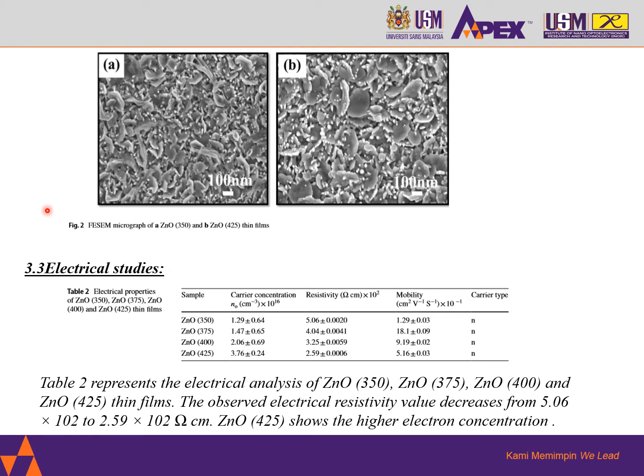Now, electrical studies. From Table 2, we can see that Table 2 represents the electrical analysis of zinc oxide 350, zinc oxide 375, zinc oxide 400, and zinc oxide 425 thin films. The observed electrical resistivity value decreases from 5.06 × 10^2 to 2.59 × 10^2 ohm centimeter. Zinc oxide 425 shows the higher electron concentration. From the table we have seen these things.